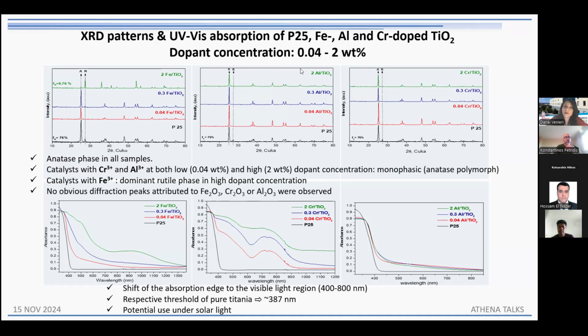Here you can see the XRD patterns and UV-vis absorbance of those catalysts. You can see also here different dopants of iron, aluminum, chromium. So anatase phase is present in all samples. Also, we didn't observe any obvious diffraction peaks attributed to the oxides. And what is interesting, of course, is the UV-vis absorbance. You may see that compared to the commercial P25, P25 is the pure titanium dioxide. So compared to that, there's a shift of the absorption edge to the visible light region.